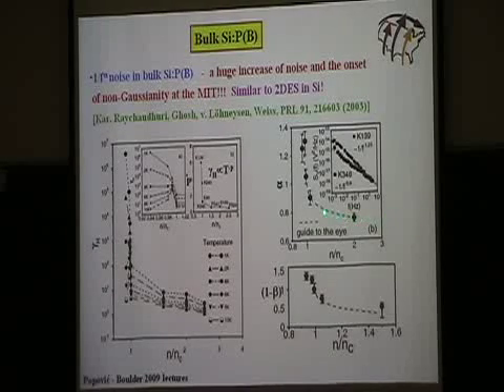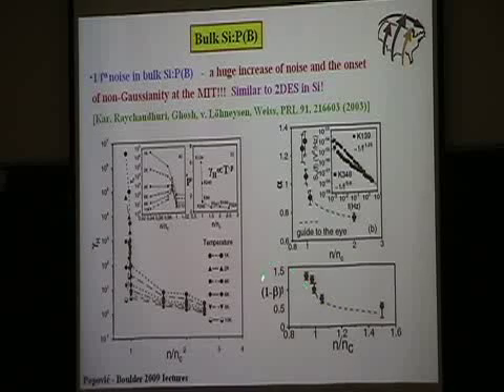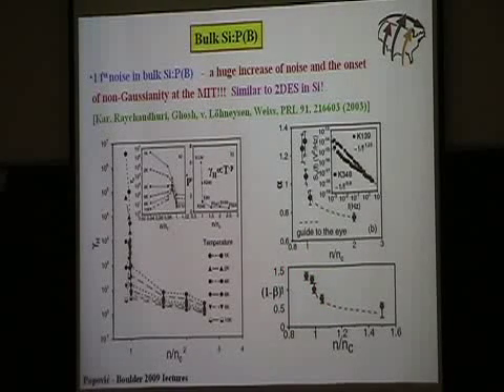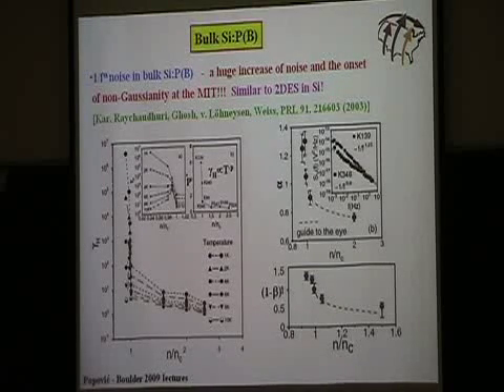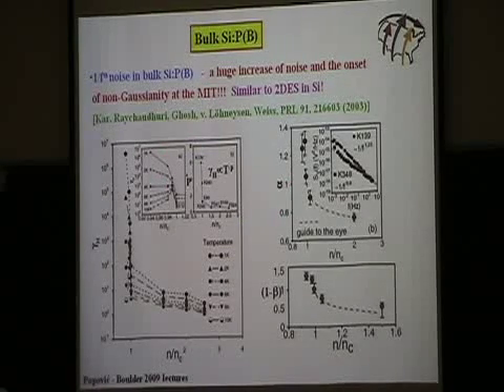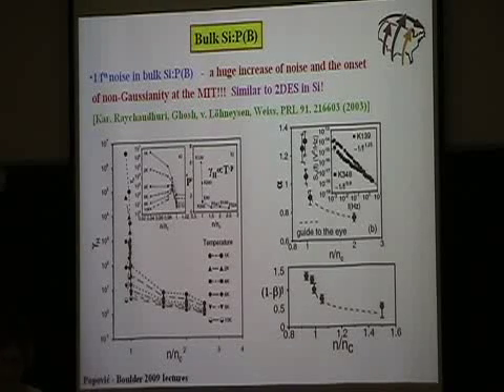Also, the exponent alpha increases. The exponent 1 minus beta goes up, which means noise becomes correlated. So it's very, very similar to what we found in our 2D system. So it seems that this may be a general feature of metal-insulator transitions if you have enough disorder. But I don't know if they'll continue working. I know that he's doing some noise work, but not on this.